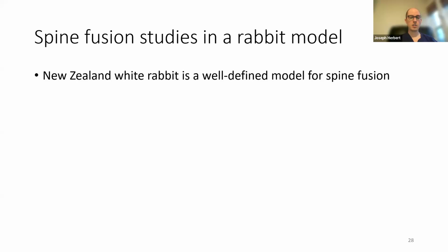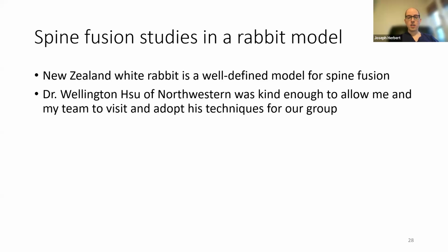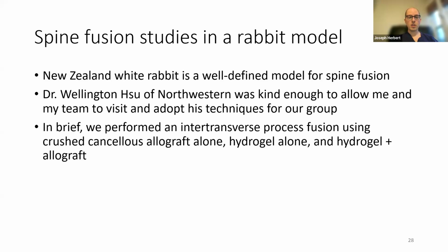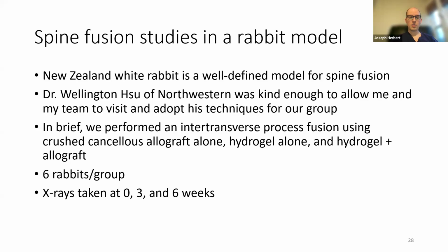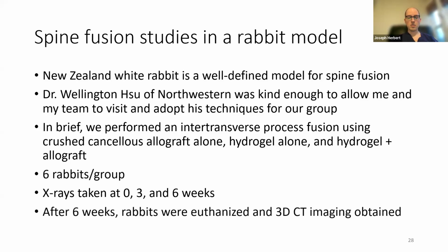They're actually pretty gargantuan. So Wellington Hsu, who's an orthopedic spine surgeon at Northwestern and an expert in this model, was kind enough to allow me and my team to visit and adopt his techniques for our studies. In brief, we performed an intertransverse process fusion, which is well defined within the model. For our experiments, we compared allograft alone, hydrogel alone, and then a mix of hydrogel plus allograft in an intertransverse process fusion. We used 6 rabbits per group, so 18 rabbits total, and we took x-rays immediately post-op, at 3 weeks and 6 weeks. After the 6 weeks, the rabbits were euthanized, and we got 3D CT imaging on these rabbits.